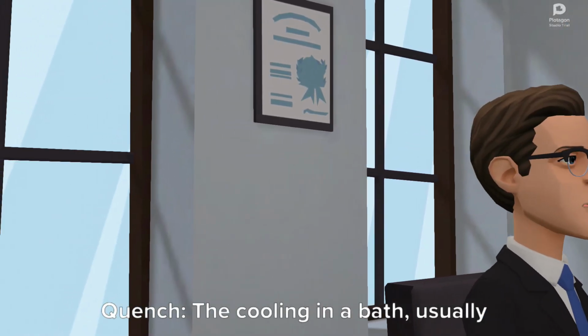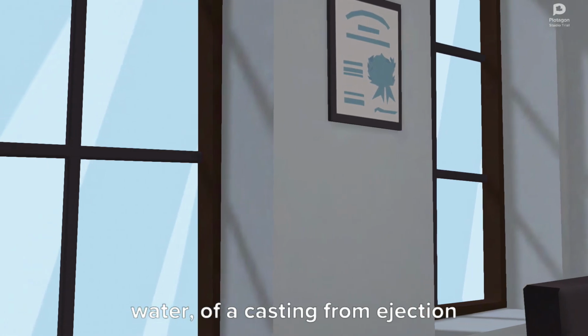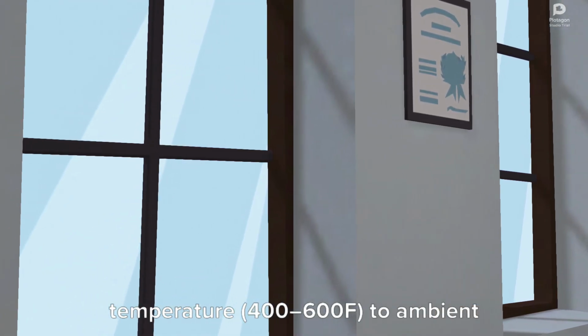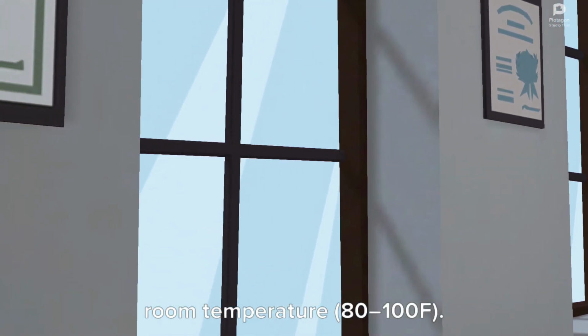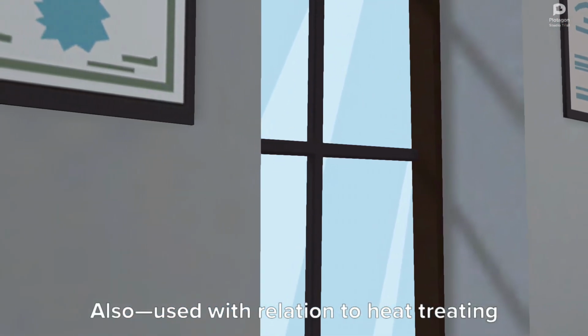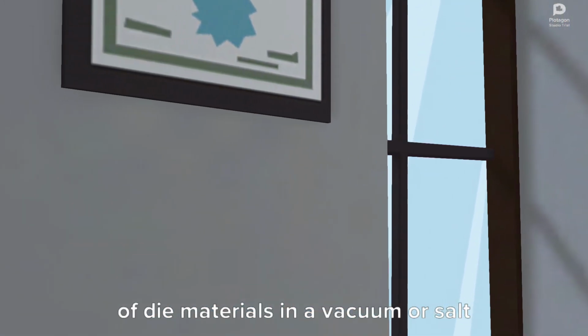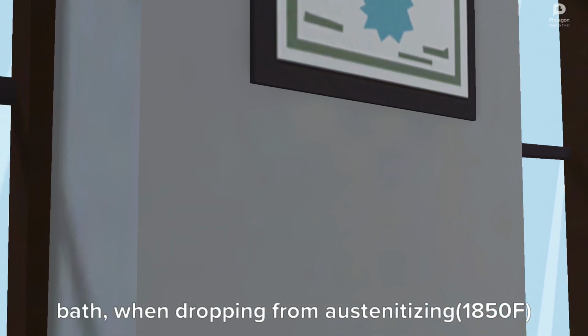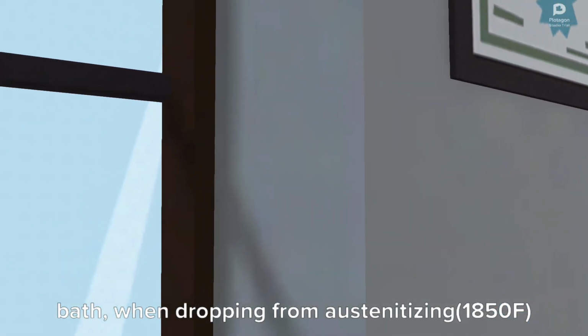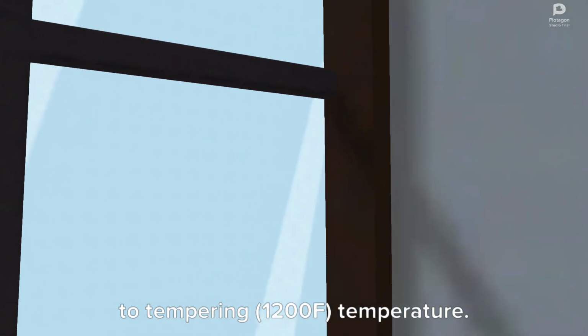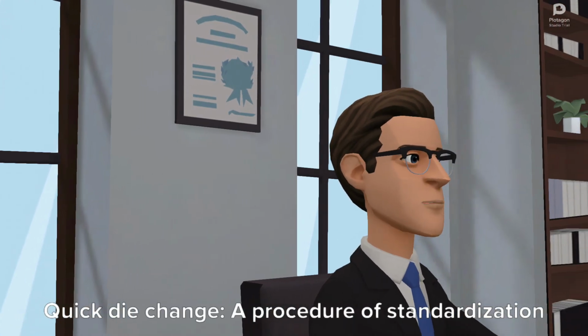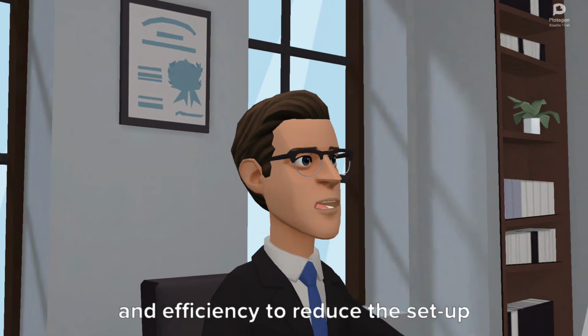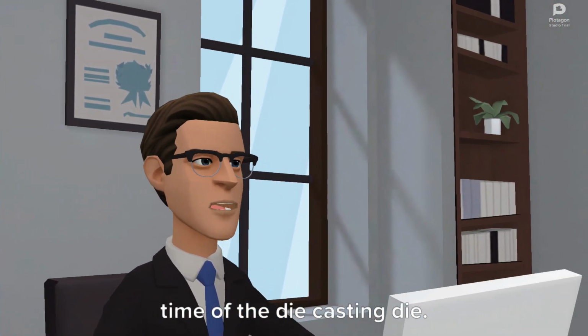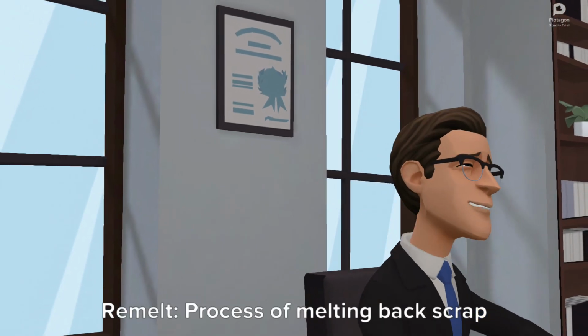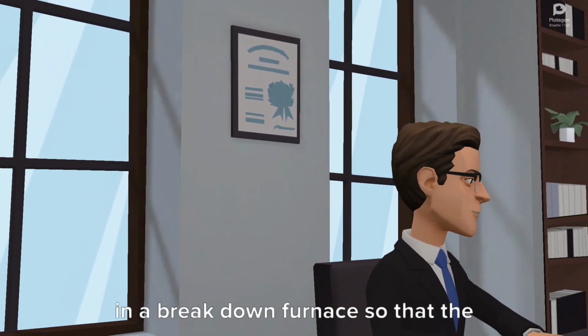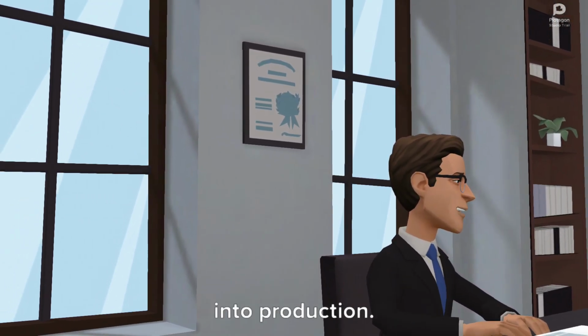Quench, the cooling in a bath, usually water, of a casting from ejection temperature 400-600 F to ambient room temperature 80-100 F. Also used with relation to heat treating of die materials in a vacuum or salt bath, when dropping from austenitizing 1850 F to tempering 1200 F temperature. Quick die change, a procedure of standardization and efficiency to reduce the setup time of the die casting die. Remelt, process of melting back scrap in a breakdown furnace so that the liquid metal may be reintroduced into production.